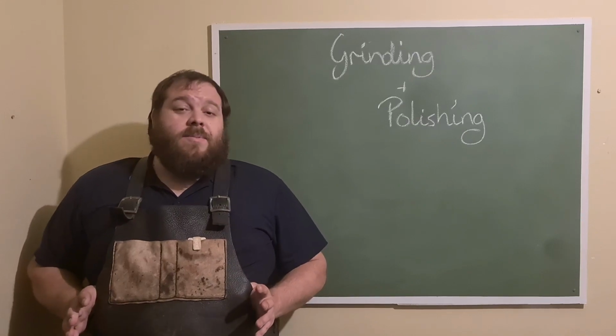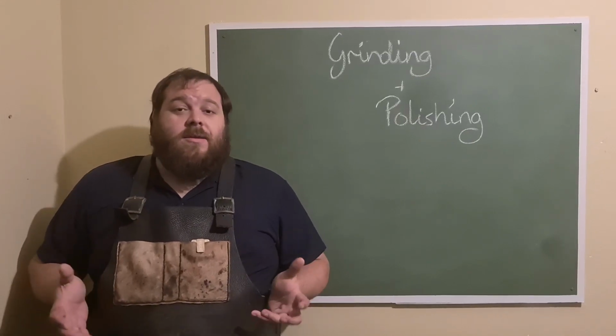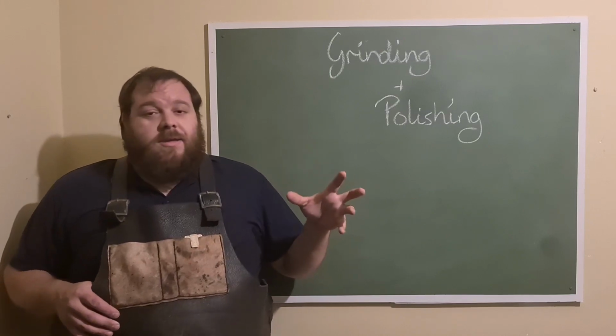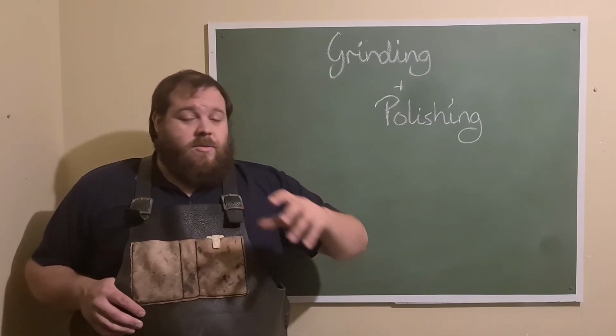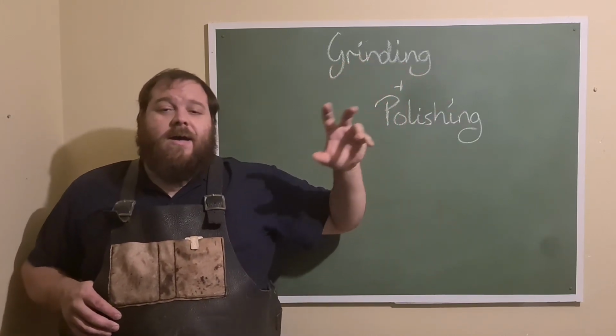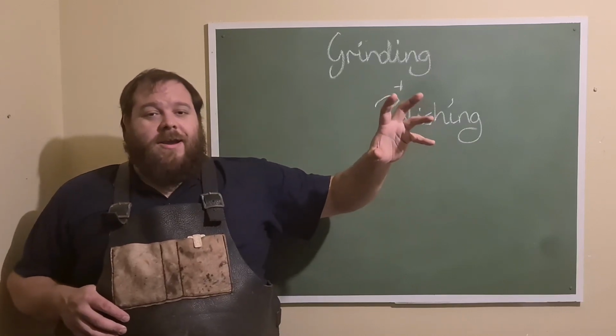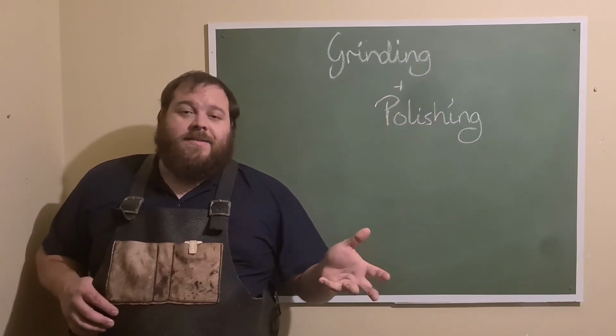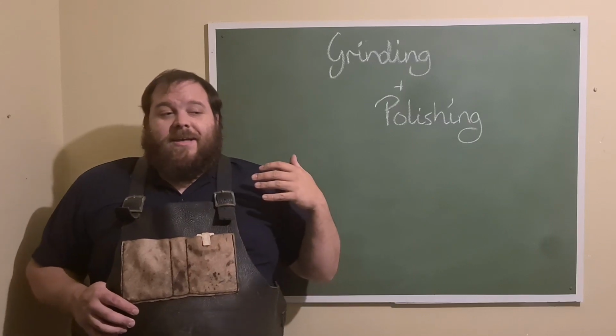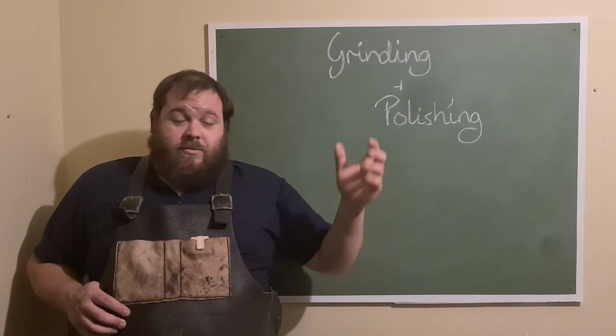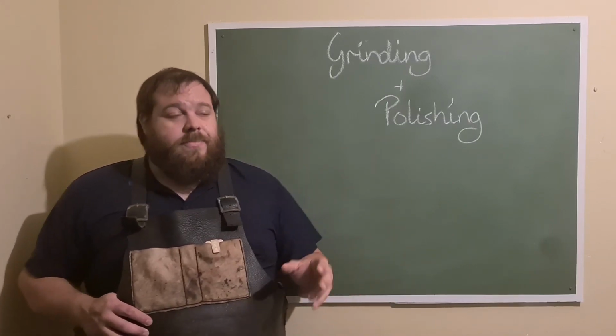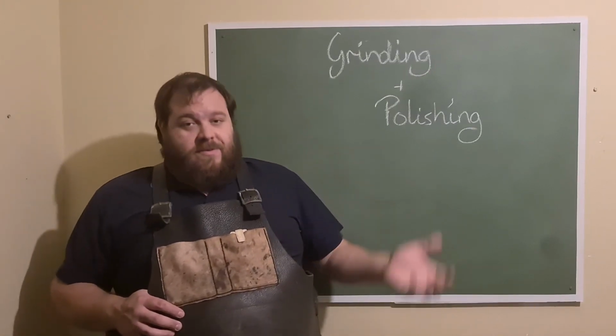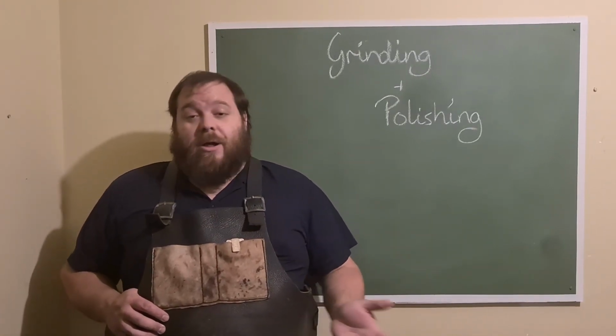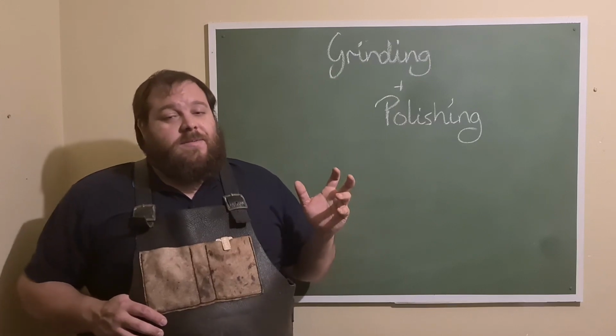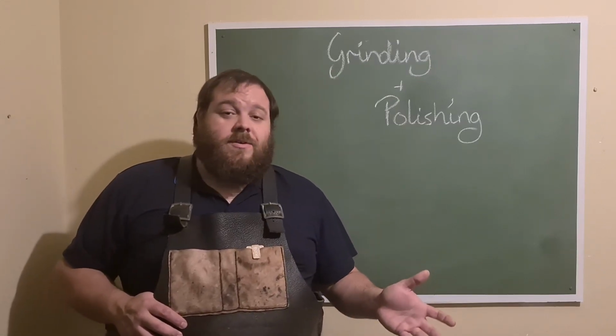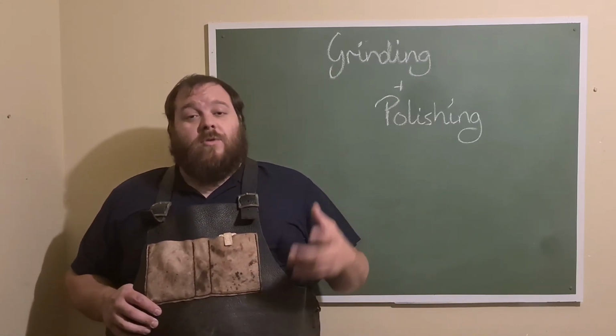Once you've hardened and tempered your blade, obviously you'll need to grind and polish it. Now, grinding can be done as normal. You can grind it with whatever abrasives you have, whatever means of grinding you have. Obviously, the hardened steel is not going to be easy to file, but whatever methods you have, if it's stones or if it's a belt grinder, you can use it. The higher grit you go to, the easier it's going to be to get to the next step, polishing. Polishing does not need to be done with stones. You can do it with stones, but it can be done with sandpaper, just like you would normally hand sand a blade.